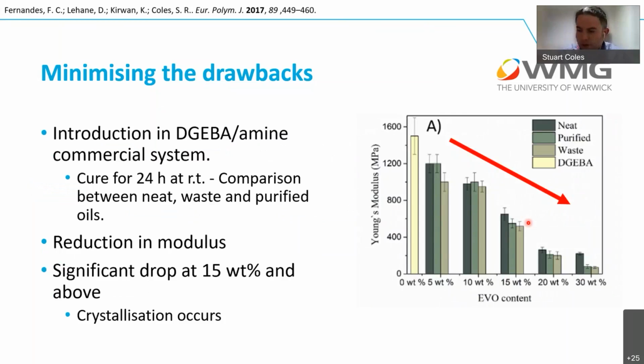So once we got our epoxidized vegetable oil, we took a very basic, straightforward approach. If we took a standard commercial DGEBA epoxy resin that was cured by an amine and then dropped in a certain percentage of bio-based material, what would happen to the resultant polymer? So we added effectively three different types of the oil: the neat oil, so we managed to source the oil before it had been cooked with, after it had been cooked with, and then after we'd cleaned it up as well. And those are the three different stages that you see there: neat, purified, and waste.